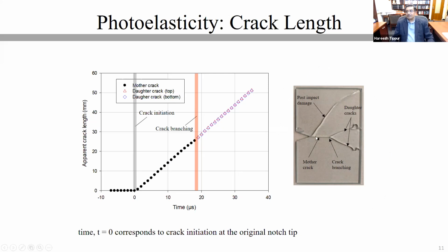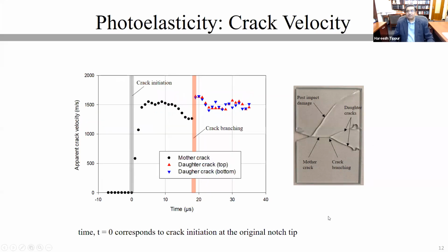You can see that the crack propagated and then branched into 2 mixed mode cracks, and there is a post-impact damage that has occurred to the specimen later on, and also some crack path wiggling that you see when it reaches the edge of the specimen because of the instabilities caused by the reflected stress fields.